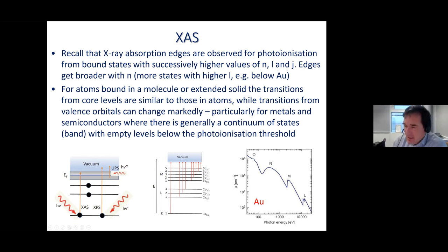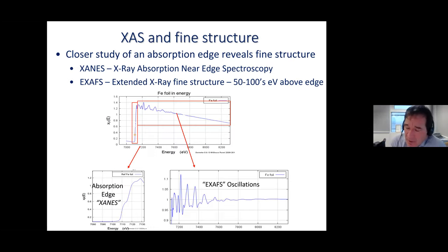So typically for metals, we'll see a progression from sharp edges to, in this case, the highest band that corresponds to the least tightly bound electrons, the highest energy states. You no longer see a distinct edge. You see a broad continuum, which reflects the fact that for the metal gold, the highest energy states are now just a band, a spectrum of energy levels. Now, one of the things we can do with synchrotron X-rays is tune the energy with great resolution through that edge. And when we start to do that, we observe that the edge actually has a much finer structure associated with it. And the analysis of the electronic structure, or the absorption pattern at the edge, provides an additional probe of electronic structure.